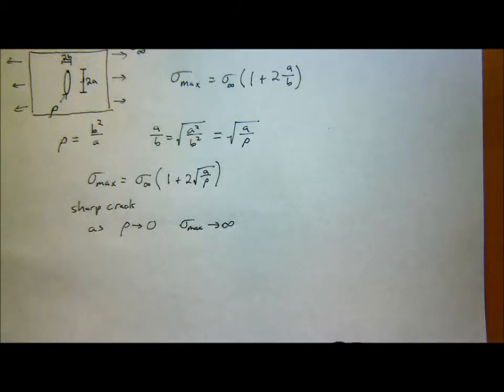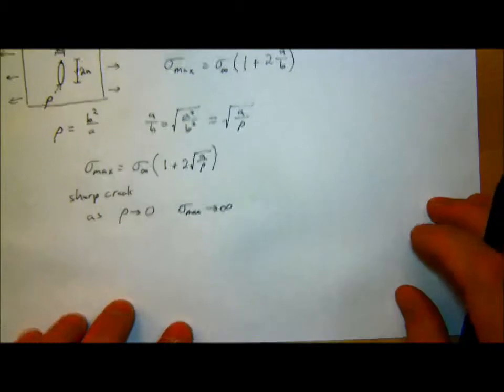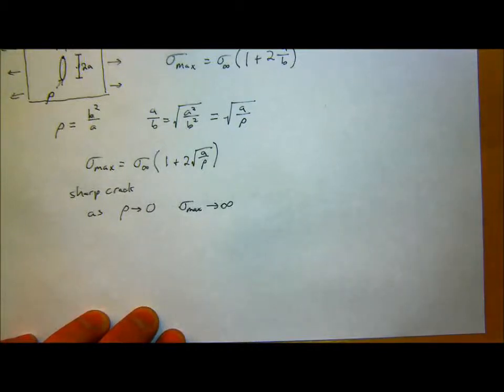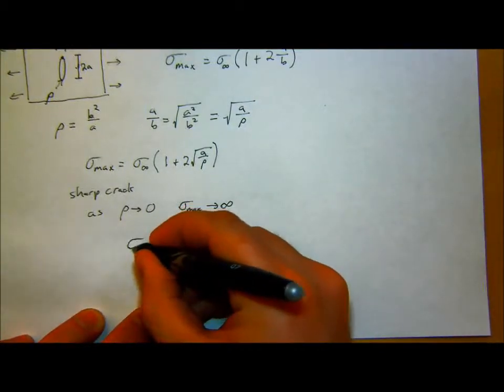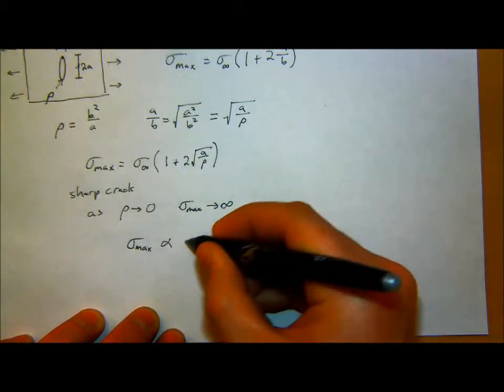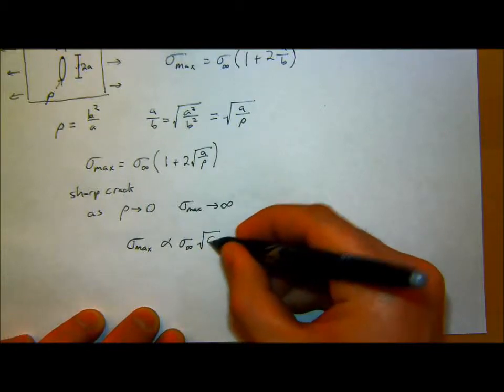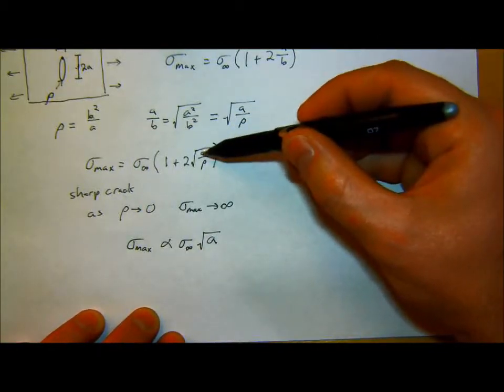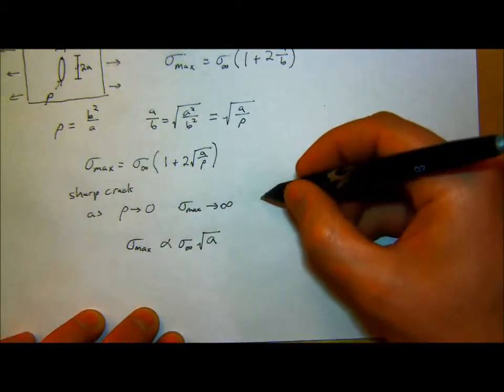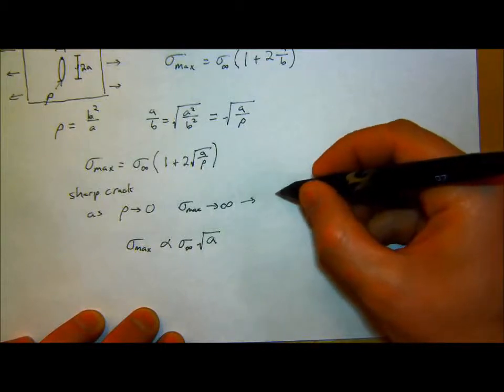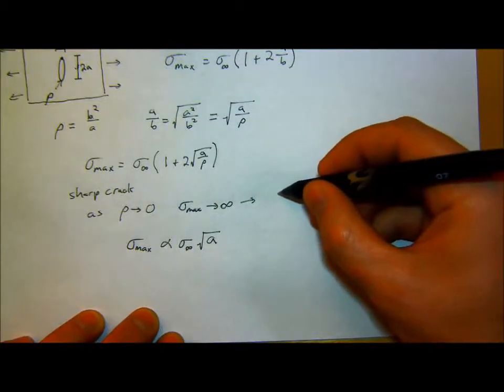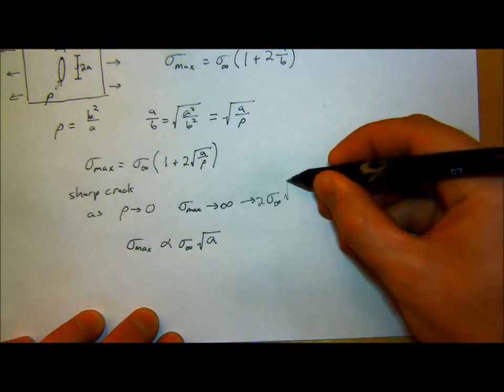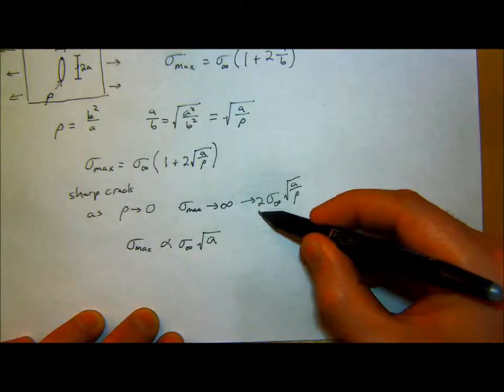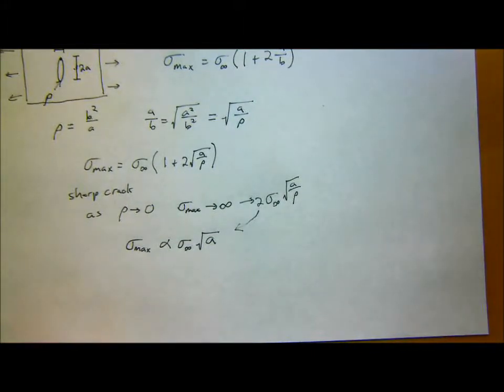Specifically, I'm going to now say my max stress concentration, sigma max, is proportional to the applied stress times the square root of A. So now I have this square root of A in there. I know as rho goes to 0, sigma max goes to infinity, but really it goes to this one term, sigma infinity times 2 square root of A over rho. But I'm going to rewrite that now, ignoring what the exact radius of the tip is, as proportional to the square root of A. There's a reason I'm doing this, and it relates to the history of how fracture mechanics started to be studied.